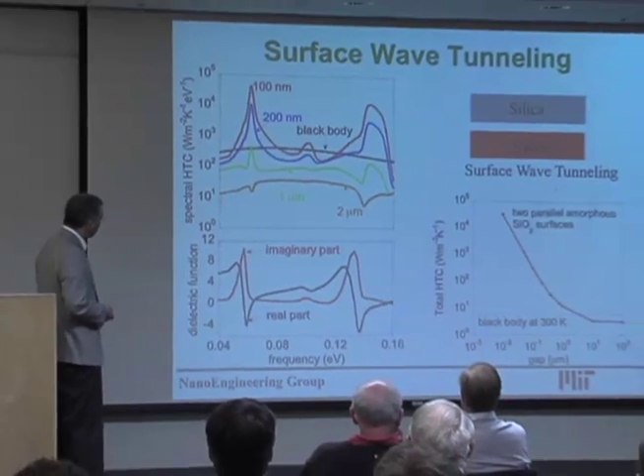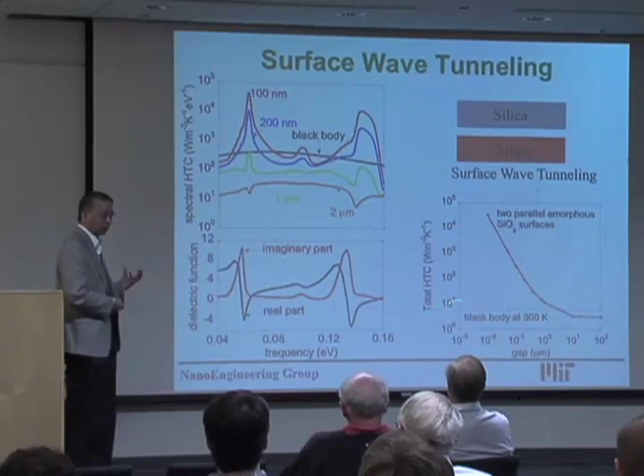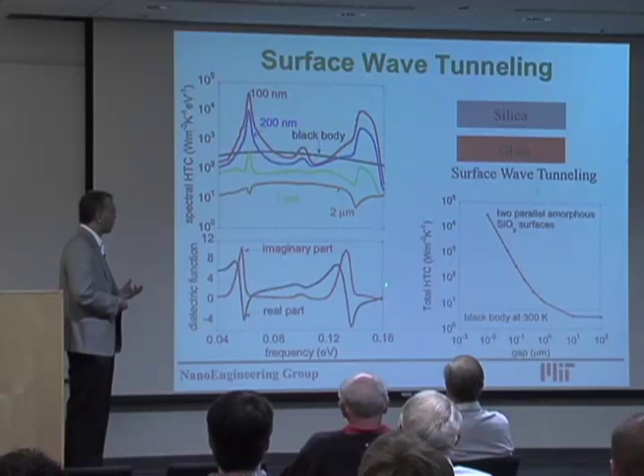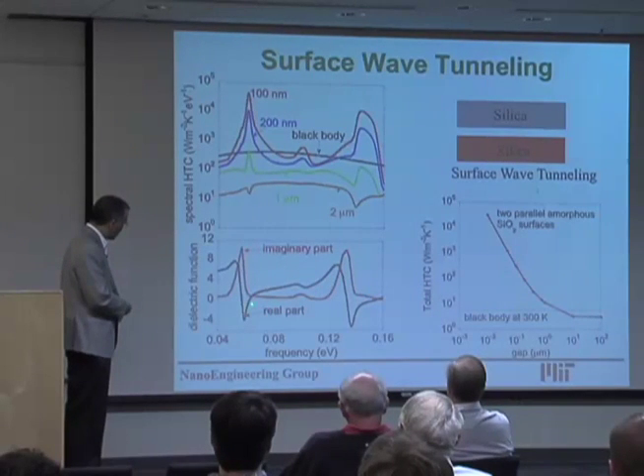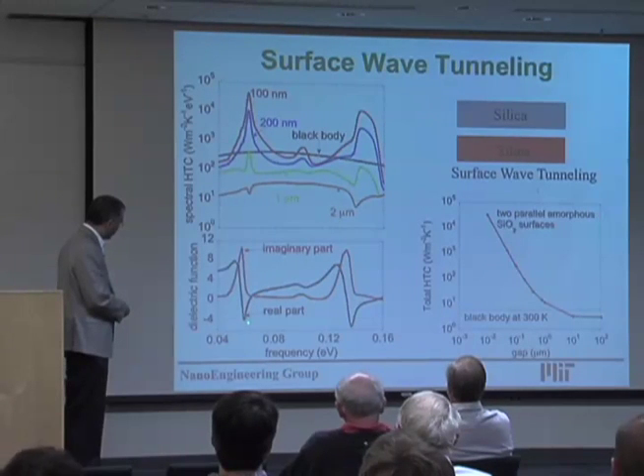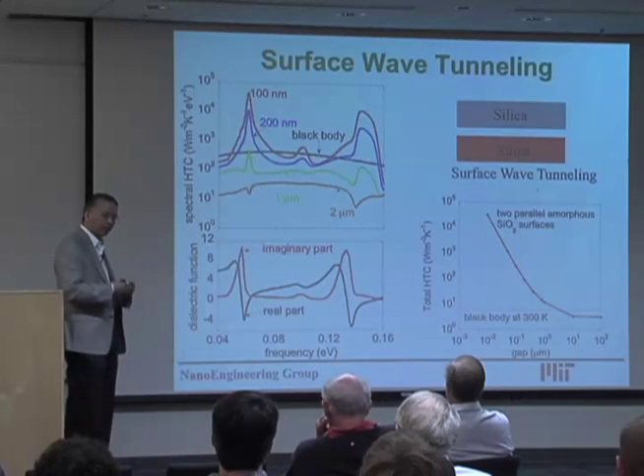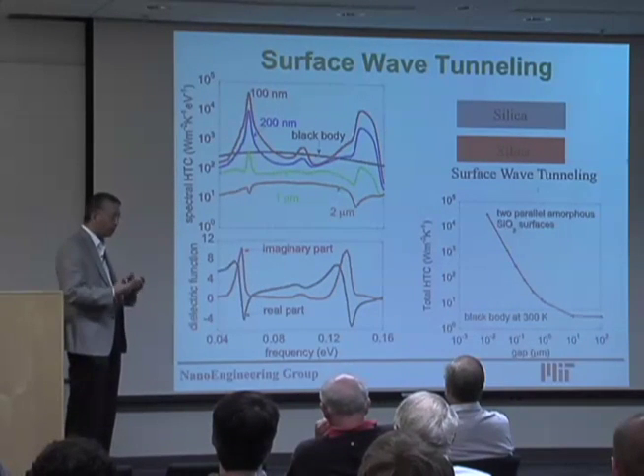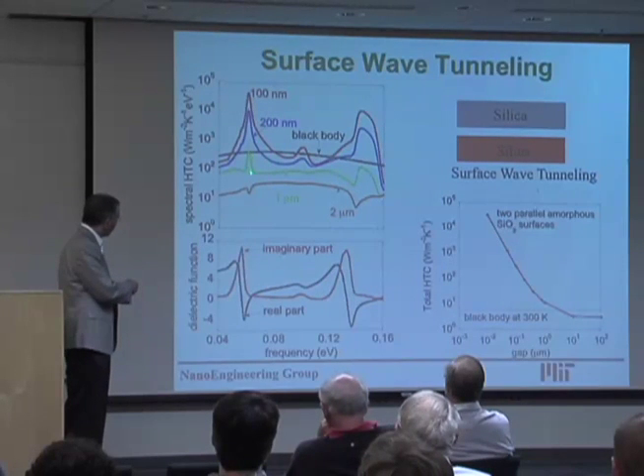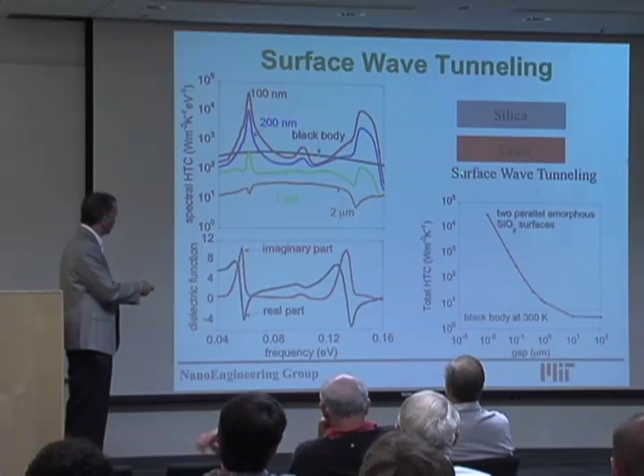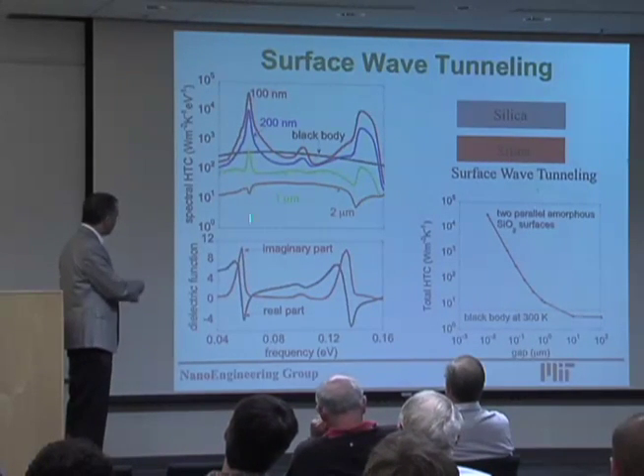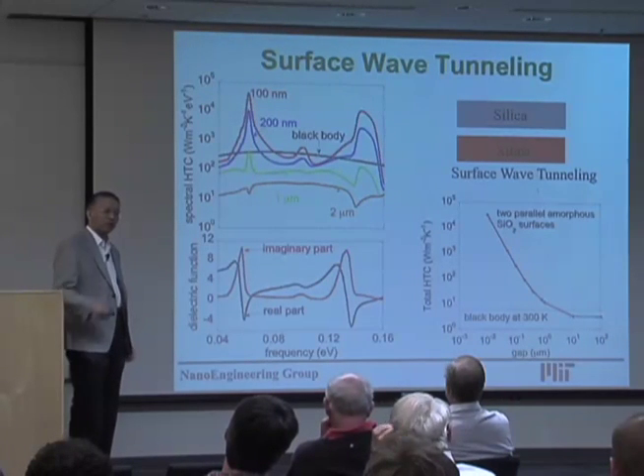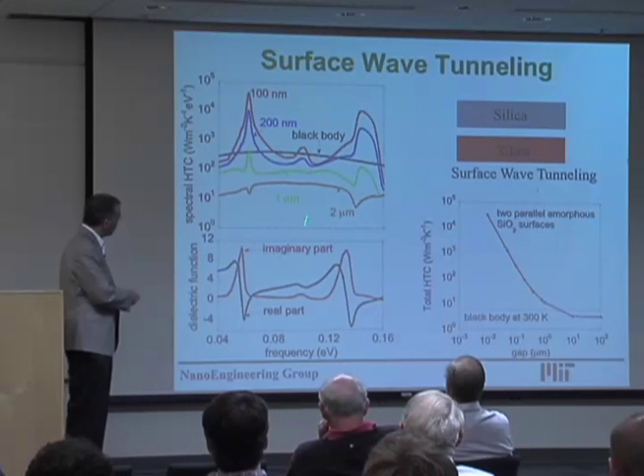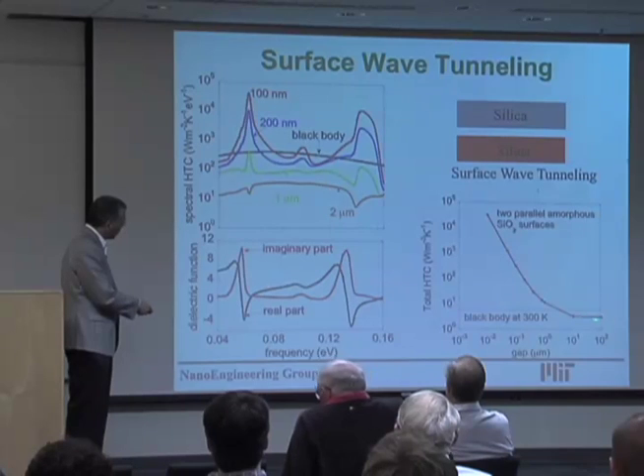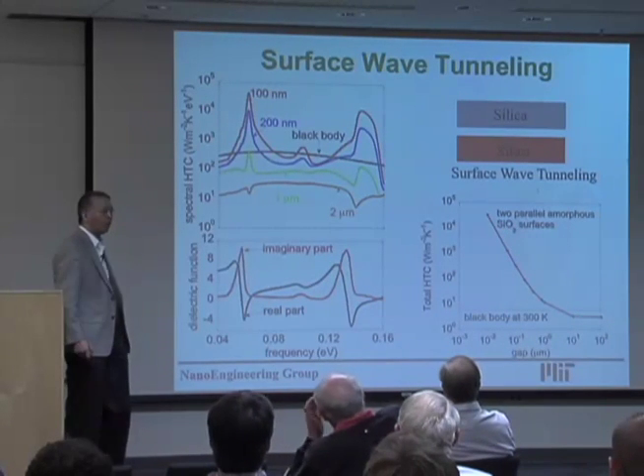But if we do that, it turns out that any polar material could have this surface phonon polariton. So even glass. This is the dielectric constant of glass, and here at about 8 micron, you can see the dielectric constant is negative, same as for surface plasmons. So when the dielectric constant is negative, you have the surface waves. And then when we bring two surfaces close by, one hot, the other cold, in this resonance range, you have much higher energy flux from the hot to the cold side. And if you integrate over all the energy, you get a heat flux from hot to cold side that is many orders of magnitude higher than the free space blackbody radiation.